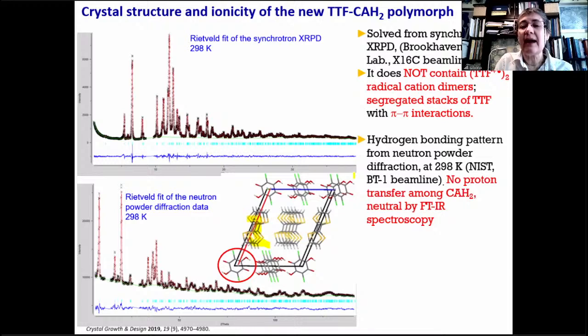So we also did neutron powder diffraction to confirm the hydrogen bonding array, because the hydrogens are essentially not visible in general using X-ray powder diffraction. So we found that each chloranil molecule has the same hydrogens as the neutral reactant in this polymorph. So there was no proton transfer. And by using infrared spectroscopy, the material is also a neutral form. It's just a cocrystal of tetrathiafulvalene and chloranilic acid.